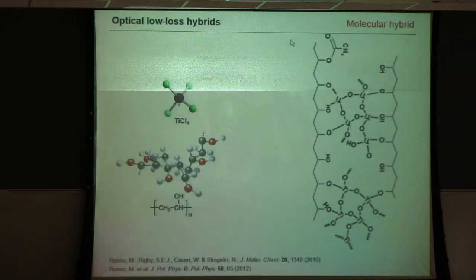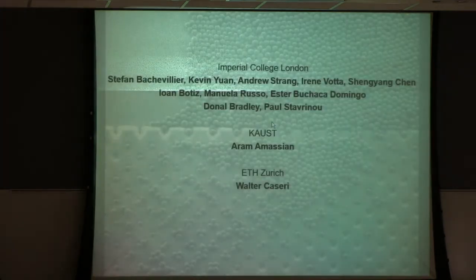In our case, we really use a superbly simple material, titanium tetrachloride, which is the precursor to titanium dioxide, which we use all the time, just white walls, etc. Then polyvinyl alcohol, used in many, many commodity plastic applications, possibly most importantly for oxygen scavenger in products.